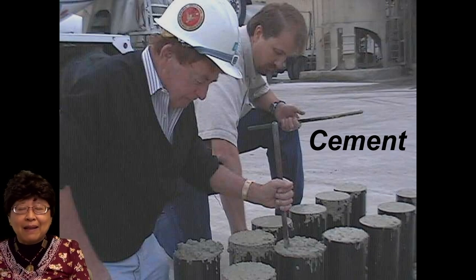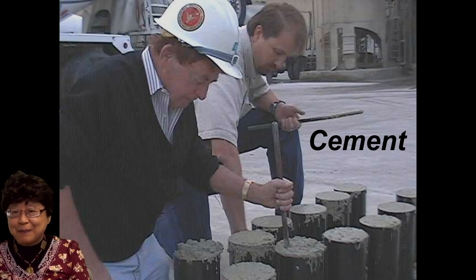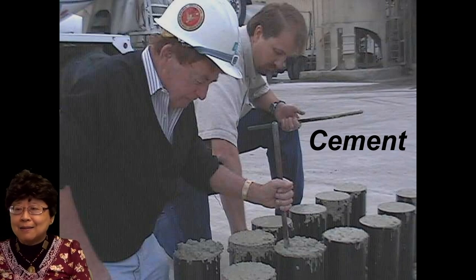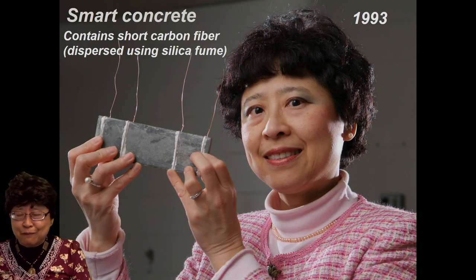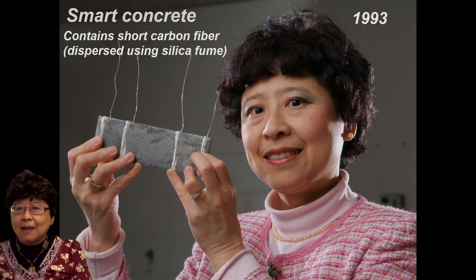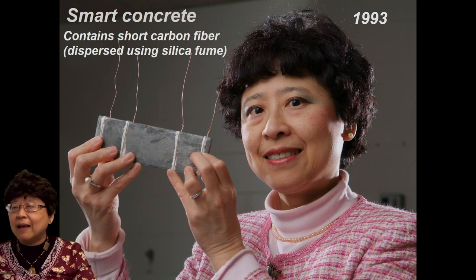I got interested in cement or concrete, even though I had never mixed or studied cement before. However, I've studied electrical behavior of materials, so I started to study cement as if it's an electronic material, a very crazy line of research. And because of that, I ended up inventing smart concrete, which is concrete that contains a very small amount of short carbon fiber. And it's important to disperse these short fibers very well in the cement, and I developed a technique for doing that.